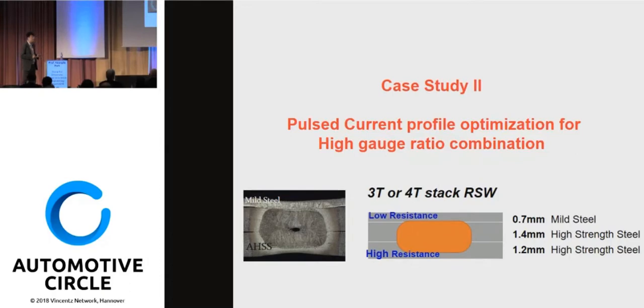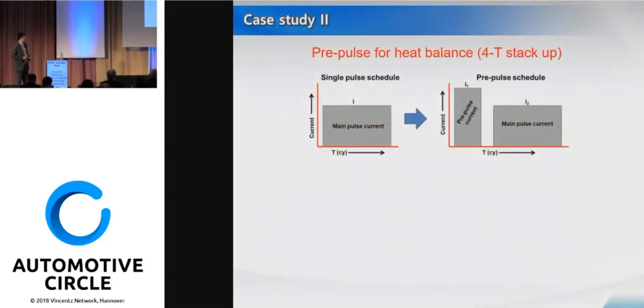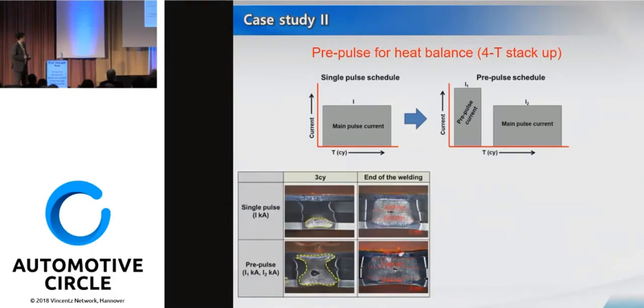So how do we deal with this case? What we found is that in mild steel, we still need a high current. So let's put the high current in for a very short time at the beginning. Then mild steel will have some heat generation, and even though it will cool down as the heat is conducted out through the electrode, it will still have it. Here's our result. In single pulse, as you expected, a lot of heat generation is concentrated on the high strength steel side, but in the case of pre-pulse, you see heat generation actually occurred at the mild steel side with the very high current pre-pulse.